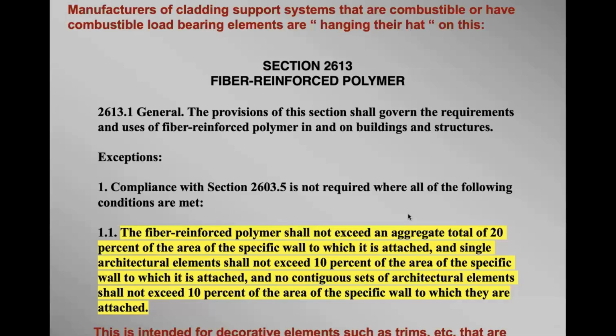So a good handful of manufacturers out there are using fiber reinforced polymers or FRPs. When I was growing up, we called this fiberglass, but now there's different reinforcings other than glass, such as carbon fiber and some other ones. And they say theirs meets the code because in Chapter 26 of the code, 2613, it said the fiber reinforced polymer should not exceed an aggregate total of 20% of the area to which it is attached. Single architectural elements shall not exceed 10% of the area specific to the wall to which it is attached. And no contiguous sets of architectural elements shall exceed 10% of the area.